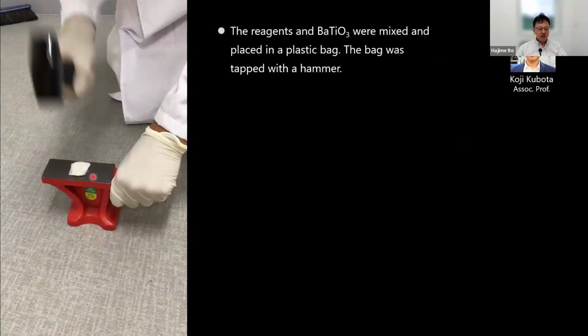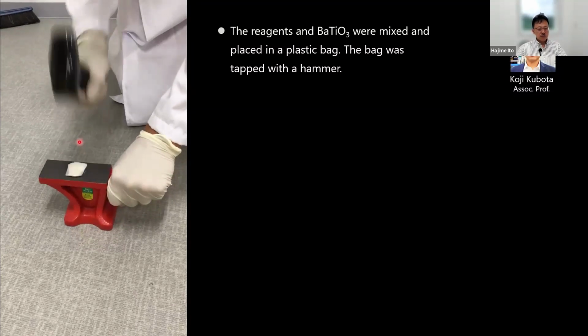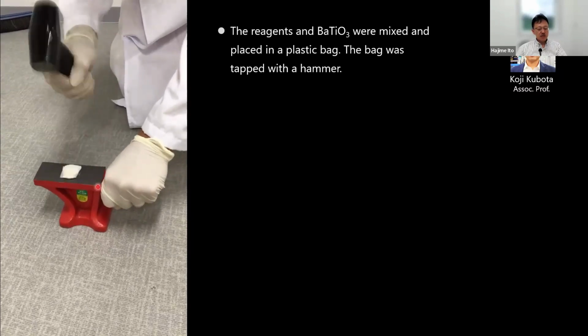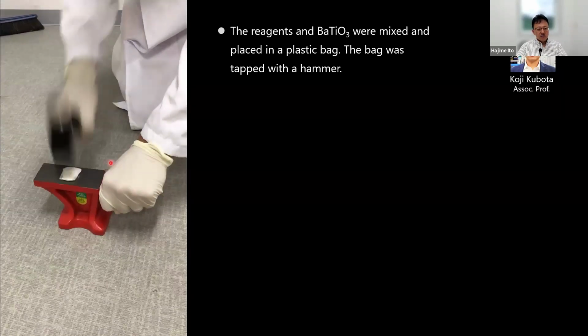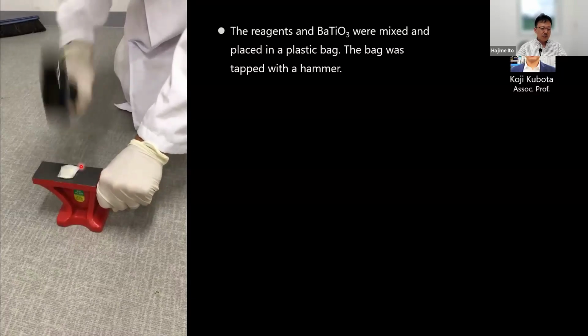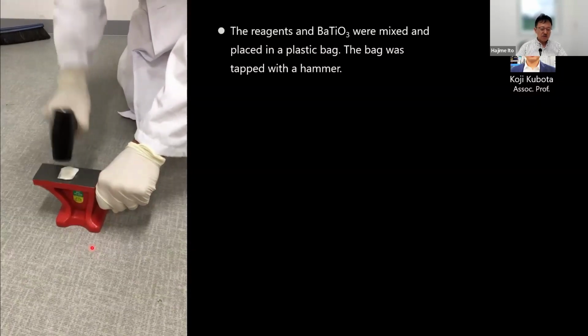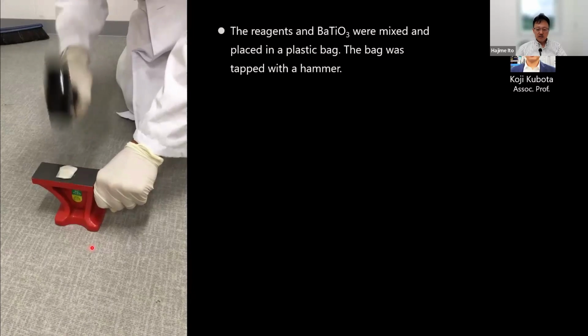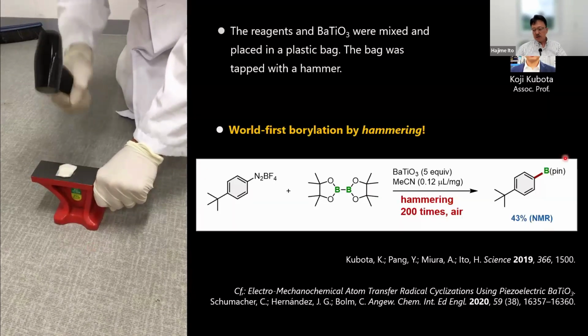I asked him to make a plastic bag including barium titanate and substrates, and I asked him to punch this barium titanate bag. This is a really crazy movie, so nobody can understand what we are doing here. But we found that boron compounds can be generated by reaction in the presence of barium titanate after hammering it 200 times. This is one of the craziest reaction conditions.